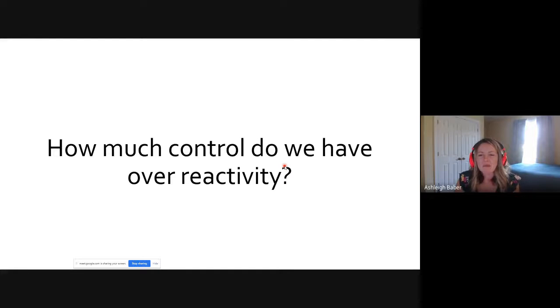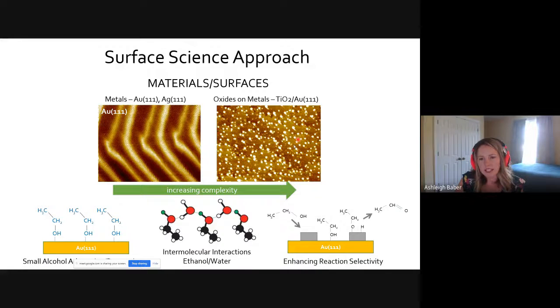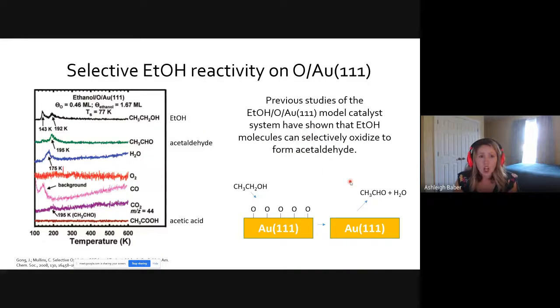Okay. So now let's get back into this whole thought process of titania on gold. So what happens when we dose titania on gold and then look at ethanol? There is some work that's been done with selectively getting ethanol to form acetaldehyde on gold 111 surfaces. And that's been by depositing reactive oxygen onto the gold surface. So selective oxidation.